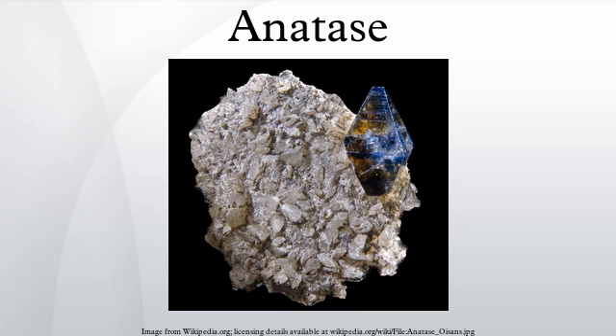Naturally occurring pseudomorphs of rutile after Anatase are also known. While Anatase is not an equilibrium phase of TiO₂, it is kinetically stabilized. At temperatures between 550 and about 1000°C, Anatase transforms to the equilibrium rutile phase, increasing its specific gravity to 4.2. The temperature of this transformation strongly depends on the impurities or dopants present in the material as well as on the morphology of the sample.